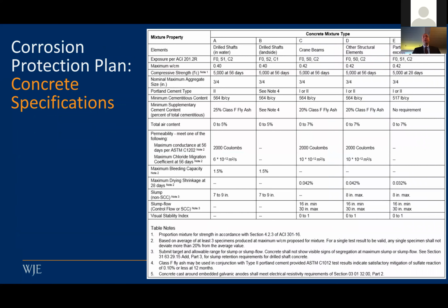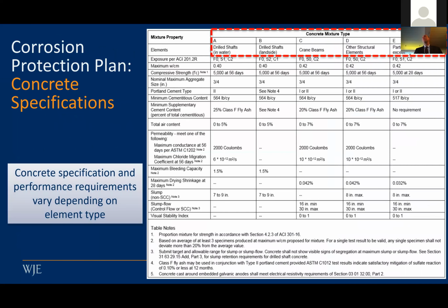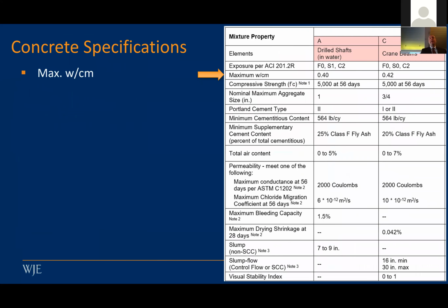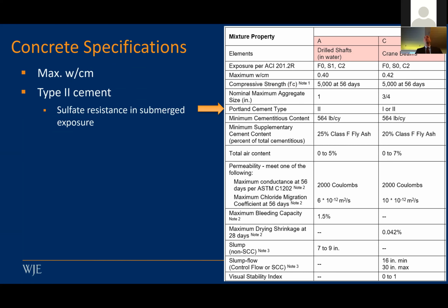And just to show how that was done, I'm going to highlight these concrete specs. Our concrete specs were performance specs for different elements, like this is what we're trying to achieve, and how they varied with the different elements. So I'm just going to highlight the drilled shafts along the water side, in the water, and the concrete, just your typical crane beam. They had slightly different water-cementitious material ratios, 0.4 and 0.42. And they had different cement requirements because the water side crane drilled shafts are in water, so they need the higher sulfate resistance.